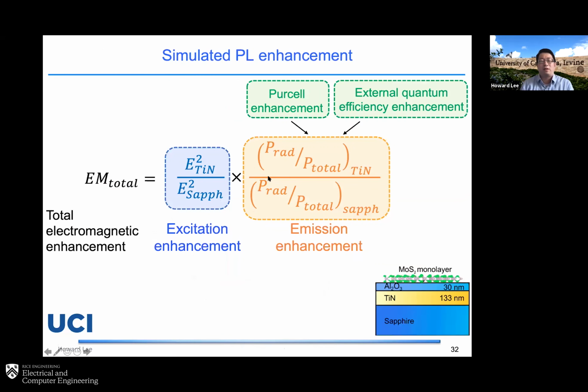So then to simulate what kind of PL enhancement you may have, you can simulate that by just looking at the total electromagnetic enhancement. Basically there are two important parts: one is excitation enhancement and one is emission enhancement. The excitation enhancement is telling you how much enhanced absorption you can get on the MoS2 due to the ENZ substrate.